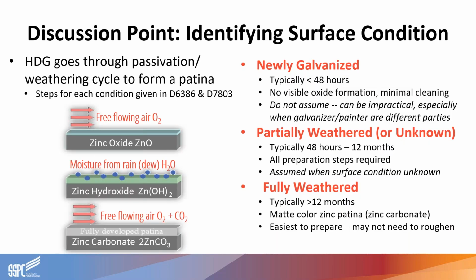Once the surface is smooth, the steps required next are to clean and profile the surface. But the steps involved and required will depend on the time that's allowed before painting, where zinc oxides and zinc hydroxides will form on the surface, and then eventually, over time and exposure to natural wet and dry cycles in the environment, it'll develop a protective patina, and that is made out of zinc carbonate.